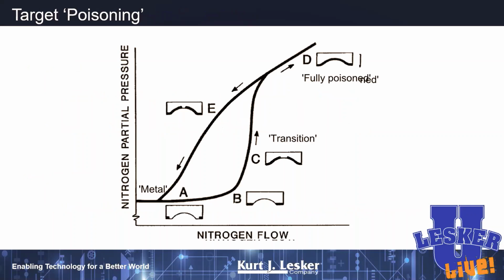Now, as I mentioned, with reactive sputtering, we're very, very interested in getting the deposition rate that we get from metals and then also make a nitride. But one of the problems that we have in doing these types of deposition is a thing called target poisoning. In target poisoning, what happens is we have a lot of redeposition of, let's say, the titanium nitride material on the surface of the target itself, which turns that surface into a nitride instead of a metal. So let's say at relatively low nitrogen flow rates, low nitrogen partial pressures, we get the behavior that we want or the deposition rates that we want by sputtering a metal with a very, very minor redeposition of a nitride on the surface of the target.